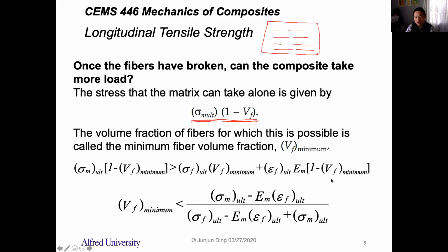So we have to compare those two. So this is the case after the fiber fails. This is the case before the fiber fails, right? So we want this one to be larger than the one before the fiber fails. Therefore, you can calculate the volume fraction of the fiber. The minimum volume fraction of the fiber can be expressed by the ultimate stress of the matrix, the ultimate stress of the fiber, and Young's modulus of the matrix and the fiber, right?